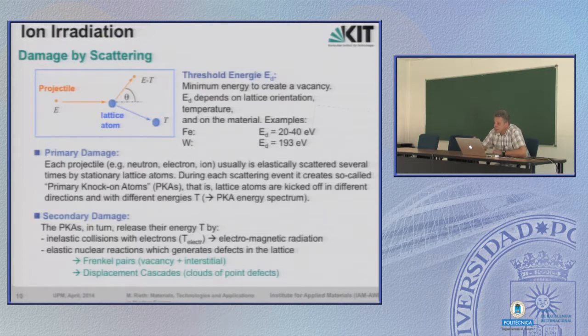They in turn release their energy either by inelastic collisions, these are electron-electron interactions which can lead to electromagnetic radiation, or by, again, elastic nuclear reactions, which generates defects in the lattice. And the most common or obvious defects are the generation of Frenkel pairs. Frenkel pairs are a vacancy, where once the atom was on its lattice site, and this is kicked off into an interstitial place, so a vacancy and an interstitial, that's what we call Frenkel pairs. But there are also more severe damages, which are called displacement cascades, and they are produced due to the series of defects which the collisions produce.